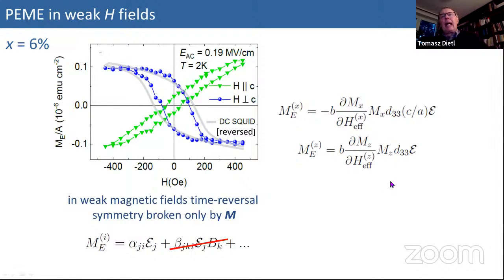And we have this proportionality to magnetization. This proportionality to magnetization is not astonishing, because as we said, if we have no magnetic field, like here we have a very small magnetic field, this should change sign under time reversal, and therefore time reversal is broken here by the non-zero magnetization. So in first linear approximation, this should be linear in magnetization, as we see from this formula, and of course expected from this general magnetoelectric effect. So it's a well understood and simple theory which can explain our observation of electric field effects in this gallium manganese nitride.